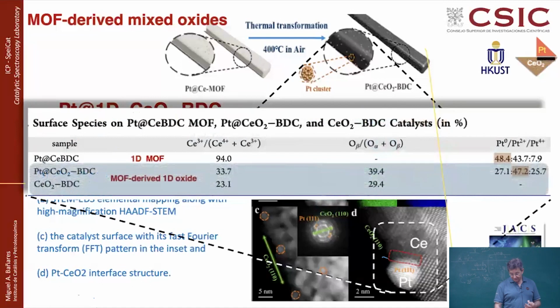And actually, in the precursor, the platinum is essentially metallic with a little bit of platinum 2+ and hardly anything of platinum 4+. But upon calcination, the platinum has a strong interaction and is more oxidized. It is essentially platinum 2+ with a little bit of metallic and platinum 4+, but clearly more